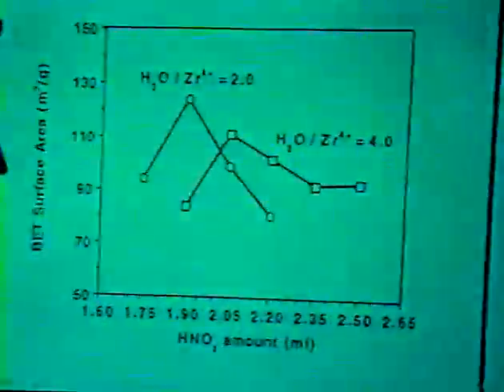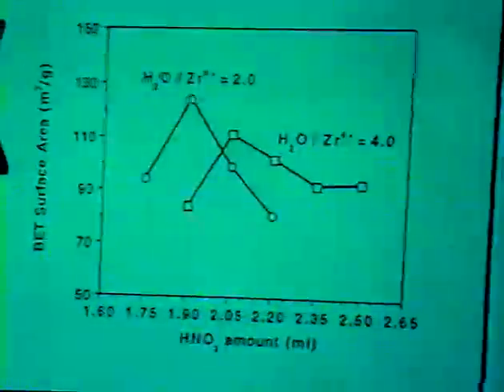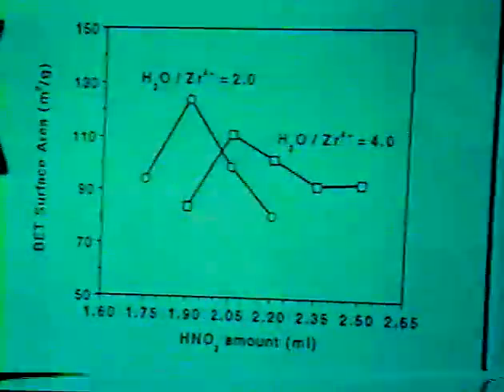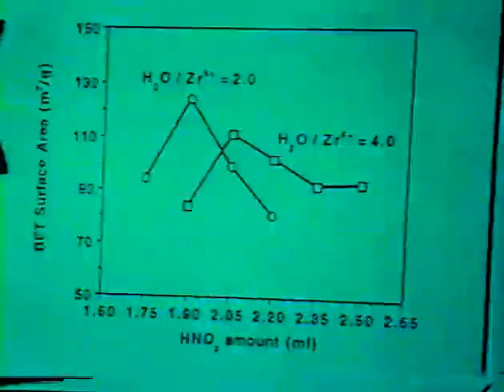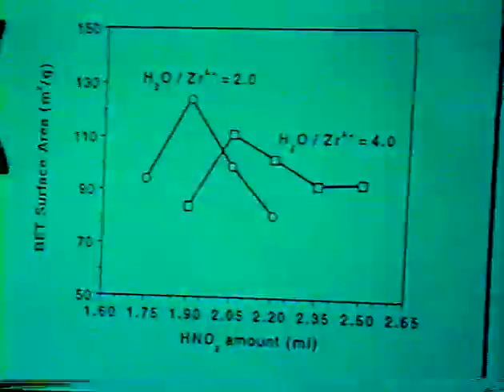As you can tell, at each water ratio the surface area goes to a maximum at a specific acid content. If you have too little acid than the optimum, then in most cases you form a precipitate, and if you have too much acid past the optimum, again there's a decline in the corresponding surface area after the aerogel has been calcined to the same condition.